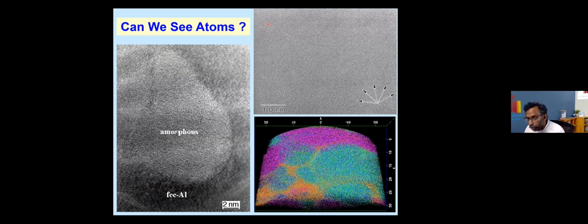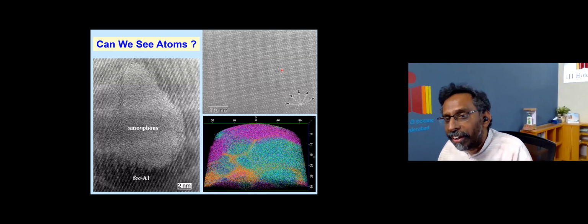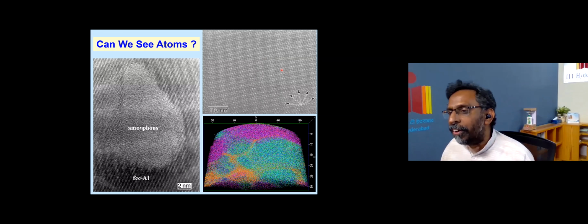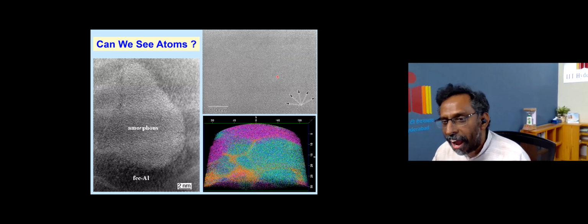To the extent that you can have materials, what you have on the top left is a quasi-crystal, we say. You have a five-fold symmetry in these quasi-crystals. When you carefully look at these dots, you will see, interestingly, pentagons. Just to tell you that materials can have a variety of atomic arrangements, and this is one such thing with special periodicity, which we call quasi-periodicity, and special rotational symmetries, which are called five-fold symmetries.